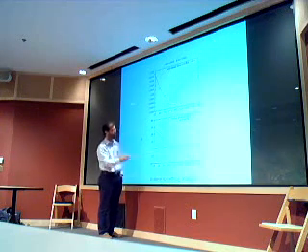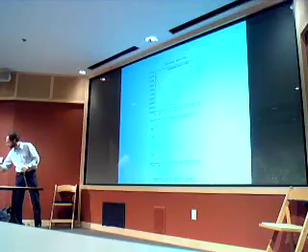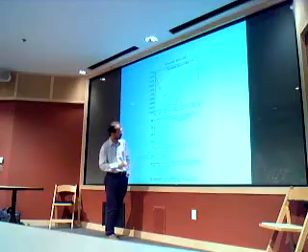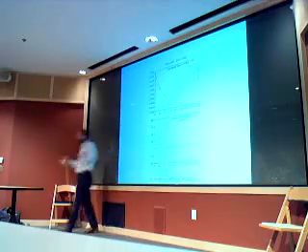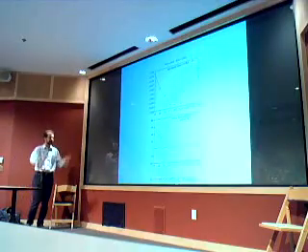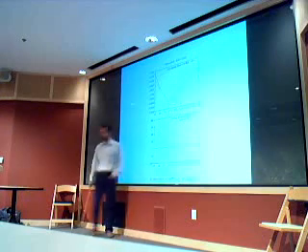The equation of state, which is derived from these points, tells you that the equilibrium geometry, the place where the stress should be zero, is somewhere between 10.2 and 10.3, while the directly calculated stress, which should be the right thing to do because it is exactly calculated from the functional that you have at that cutoff, gives a result which is way off from that value.